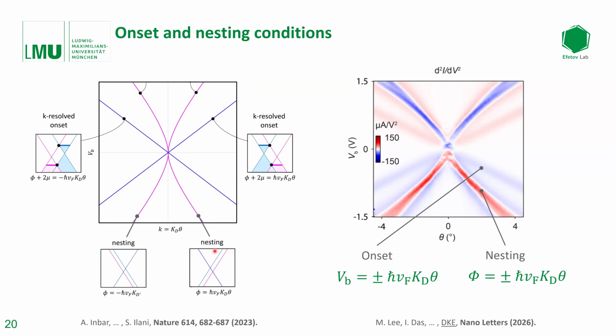This is the condition where the top and bottom layer align, and the two bands, in particular the Dirac bands that are linear and run for a long period in momentum space, are directly parallel to one another. This allows for a lot of momentum and energy resolved conditions, and this results in these hourglass-shaped features, which depend mainly on the electrostatic potential. And of course, in the data you see these very pronounced hourglass-shaped features.